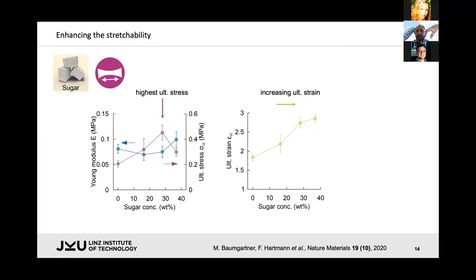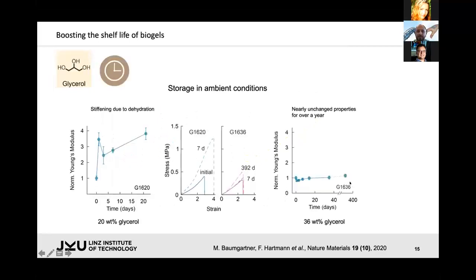And with this, again, improve and increase the mechanical properties. However, you will still have a hydrogel, which is prone to dehydration. So in the long run, this material will not work for you unless you add a humectant such as glycerol that is also food safe. So if you add actually a lot of glycerol, if you replace basically a large fraction of the free water by glycerol, then you can achieve a hydrogel that is very, very stable in its properties.